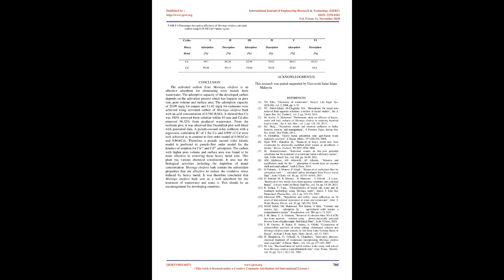For this reason, adsorbents attract metal cations, mainly in the cationic form Cd2+, and they more easily get adsorbed onto the adsorbents. The Cd2+ adsorption on activated carbon can also be described by an ion exchange mechanism. The main functional groups on the surface of adsorbents are the carboxyl, hydroxyl, and methoxyl groups, which are responsible for ion exchange onto their surface. The mechanism taking place on adsorbents is shown in the equation.